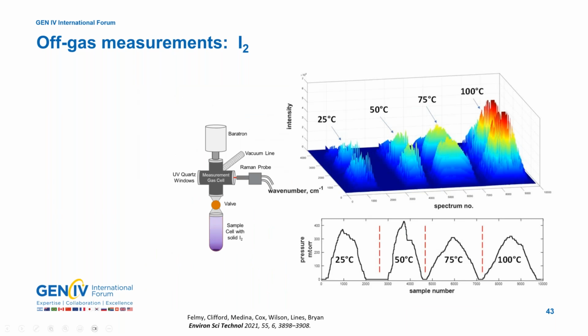The next slide shows a series of variable pressure measurements. This is pressure as a function of temperature of measurement. This is the Raman spectrum as a function of both temperature and pressure. The pressure is shown here. We're measuring this with our gas manifold line. We have a Raman probe with our gas measurement cell. We have a valve system where we can meter iodine into the gas phase. We can measure that with a Baratron gauge.